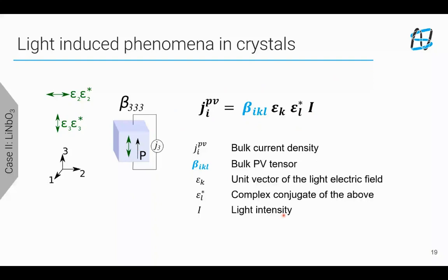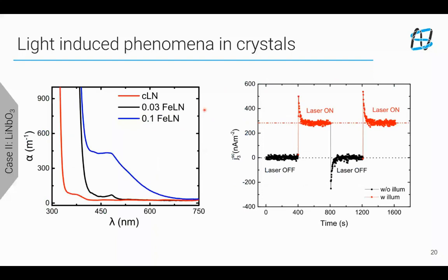As usual, we have done absorption spectroscopy, and we can see that this is the visible wavelength of light that we can all see, and this is what comes to Earth mostly. Exactly in that spectrum, we can see an increase in absorption when we put a transition metal or a defect incorporation into lithium niobate. As I said: structure, symmetry, defects, and properties. It is also the defects that you incorporate in the crystals in order to make best use of their intrinsic properties.